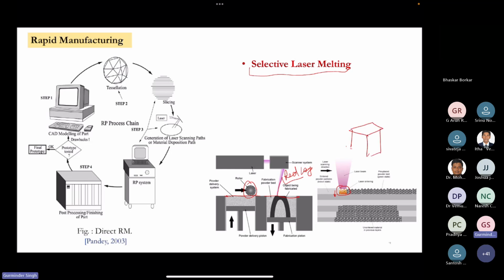But this process is valid only for those materials which can be easily absorbed, which have a good absorption coefficient, which can easily absorb light photons, like steel, which has less thermal conductivity. It can easily absorb titanium, which has low thermal conductivity. It can easily absorb the energy and melt the powder easily.